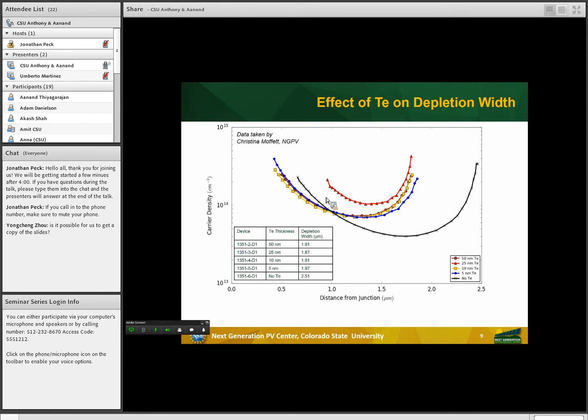To further support the DFT modeling results, we can look at the effect of tellurium on the depletion width of the CdTe device. Looking at the plot, we can see that the line labeled in black has no tellurium deposited and will lead to a greater depletion width. When we add a tellurium back contact to the CdTe, as shown in these other lines, we see a decrease in the depletion width, which in turn will lead to the device working more efficiently.